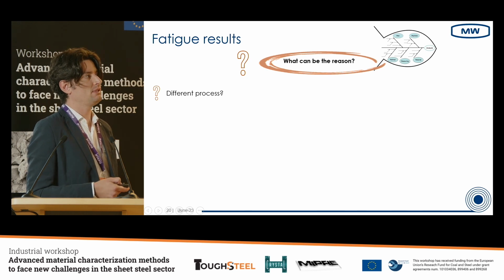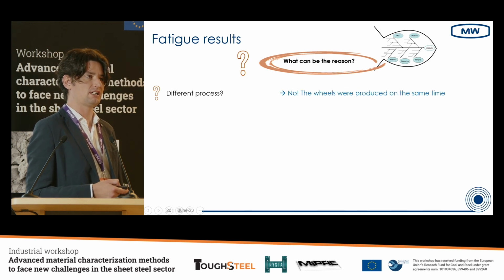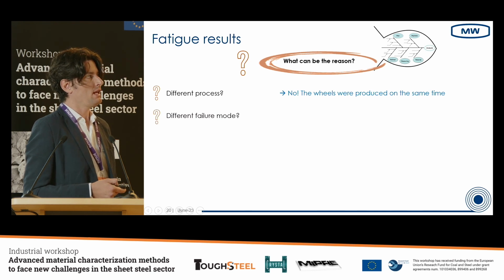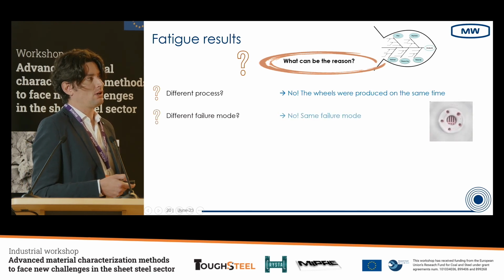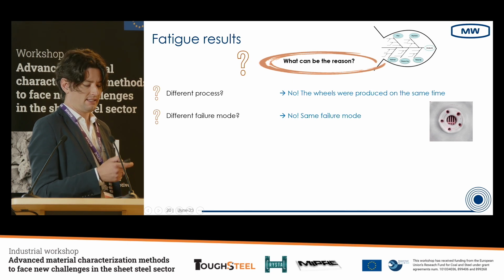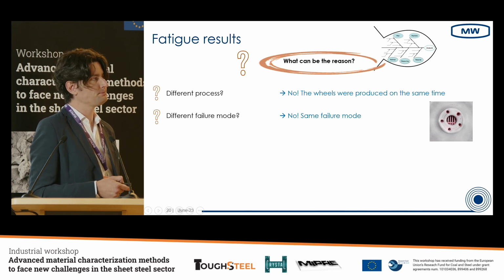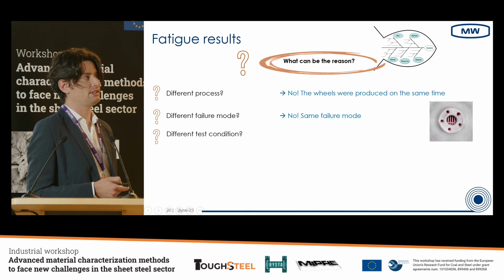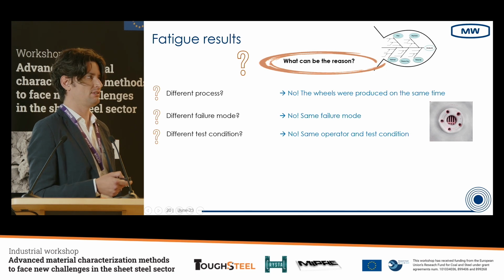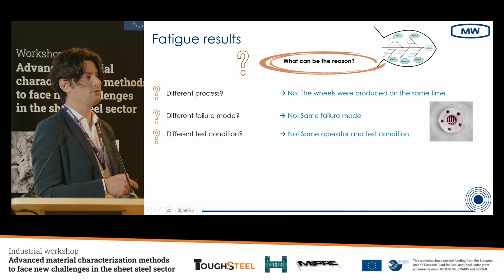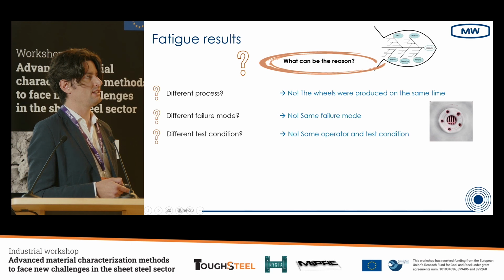So can it be a different process? No, because the wheels are made at the same time, in the same press, in the same batch. Different failure mode? No, in this case we analyzed all the wheels tested and they all have the same failure mode. Different test condition? No, because the operator is the same, the test conditions are exactly the same, on the same bending machine with the new screw and so on, so the tests are really identical.